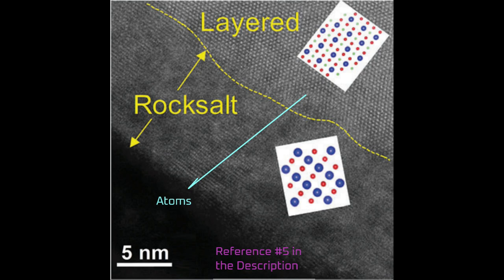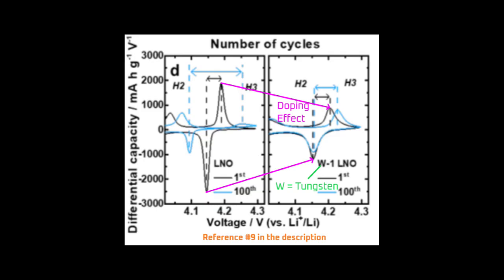As with the concentration gradient core shell structure, the shell increases the stability against the electrolyte much like a protective coating would, which in turn increases thermal stability and cycle life. This coating effect doesn't explain how the heterostructure cathode prevents cracking caused by expansion and contraction. The paper cites an answer for this, which is a reduction in a specific type of phase transition that occurs at 4.2 to 4.3 volts, which would reduce expansion and contraction. However, tungsten may have another impact here that's not stated.